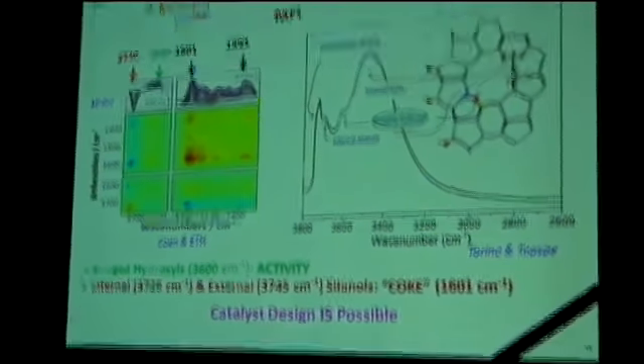We did that, and I will skip this slide. We just produced two materials with the same silicon to aluminum ratio and the same particle size. Everything that we could control was the same, except the level of defects, and you do that by just changing the synthesis condition. In one case you do the synthesis under the normal hydrothermal caustic solution, and in the other you use fluoride ions, and the fluoride ion gives you far fewer defects, and lo and behold, the catalyst is much more stable.